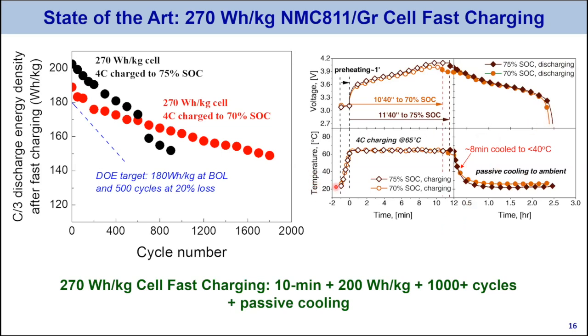Okay. Now, if you look at the temperature curves, first you see an amazing result. During 4C high current charging, the cell temperature remains nearly at 65 degrees Celsius, despite the fact that the test cell is sitting in stagnant room air. So in other words, there's no liquid cooling, and there's not even a fan blowing air towards the cell. It's all under natural convection, and you can still dissipate a very large amount of internal heat generation. And the reason is very simple: the temperature difference driving heat dissipation is huge. The cell is at 65, ambient is 25, okay? So you enjoy a very large delta T, basically.